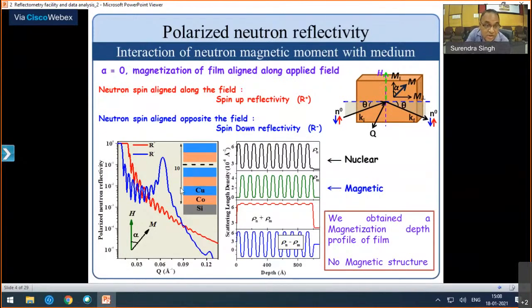Another thing - since it's a multi-layer, we have magnetization along the field direction in this case, so we have nuclear as well as magnetic potential. The R plus is spin up - this red plot over here comes due to the plus sign, the scattering length density, nuclear scattering length density.